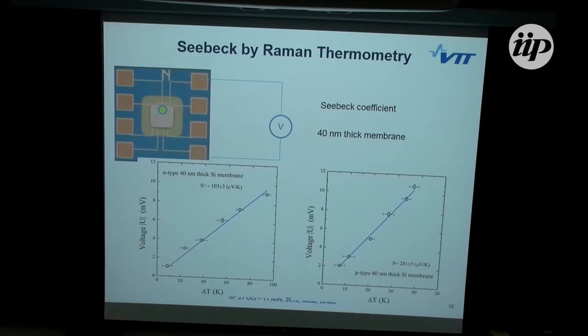So there is an electrical contact here and here, and now when one puts the laser spot close to this contact, one knows the temperature here and assumes that the temperature there is not high, let's say, the bath temperature. Then, by measuring the voltage between these two edges, one can get the Seebeck coefficient. This doesn't give the proper number because one cannot put the laser spot on top of the contact, but it gives a worst-case estimate. For N-type, this was 100 microvolts per Kelvin, and for P-type, a little bit below 300. When one sums this, it gives roughly the same number as we measured from this test device.